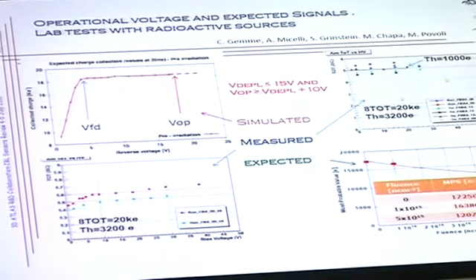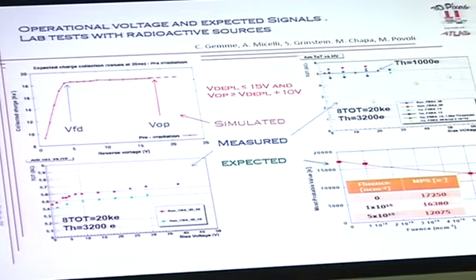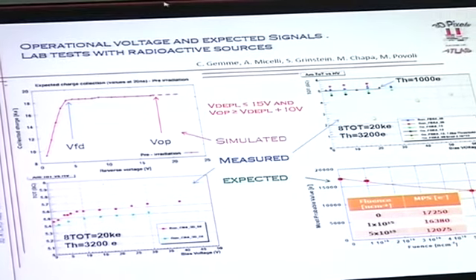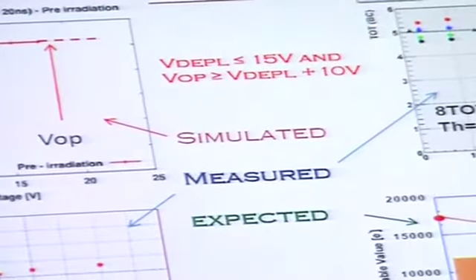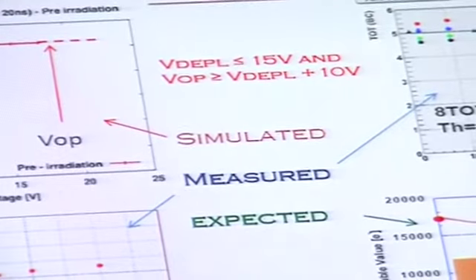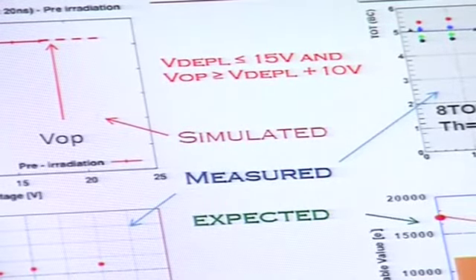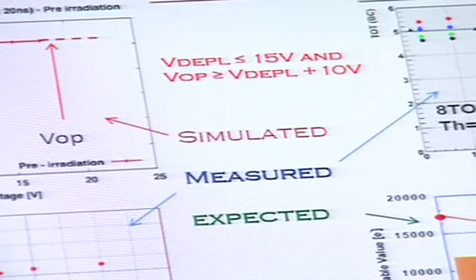Here is the same, so these were FBK sensors. These are CNM sensors. These are FBK sensors. Probably the turn on here is less evident, but again it's showing that we are, in fact, at 20 volt here in the plateau. And this blue curve here was taken with a threshold of 1,000 electrons, because I think we need to take advantage of this lower threshold to make sure that we are getting the maximum efficiency. And we saw that at the moment in which we didn't do that, during the test beam, the efficiency went down. I think the message here is that the threshold is not changing with bias voltage.